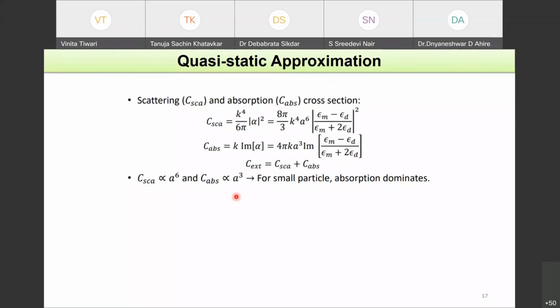So they tell you a lot about the characteristics: the scattering cross-section scales as the sixth power of a, which is the radius of the particle, whereas the absorption cross-section scales as a cubed. It means when the particle is small, absorption will dominate, but as your particle keeps increasing in size, scattering will dominate. So you can understand that based on your requirement, you can design nano antennas which can scatter or absorb light.